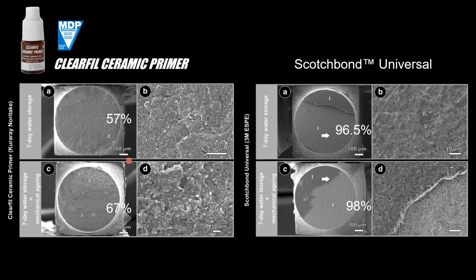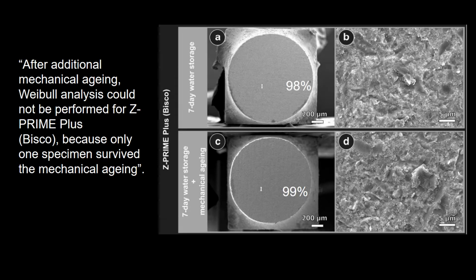He does not give the bond values in the study, but you can tell in reading it that he says profusely this was the most stable and high bond. Now, with Scotchbond Universal, it started failing just in water, coming off at the interface of the zirconia. And 98% after the aging came off of the zirconia. So for some reason it wasn't a durable bond to the zirconia. With Z Prime Plus, their quote was, after additional mechanical aging, analysis could not be performed for Z Prime Plus because only one specimen survived the mechanical aging. So you see a pretty high failure rate here, 98% when they just put it in water and 99%, and I means it's on the interface, which is the zirconia. So it's coming off the zirconia rather easily.